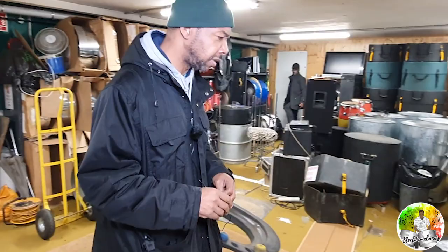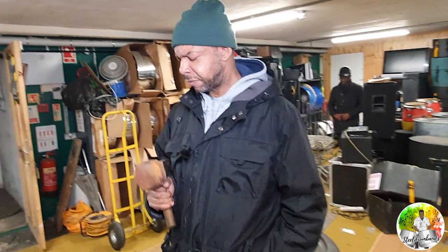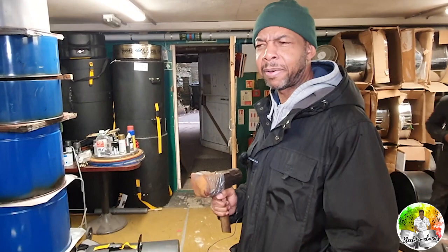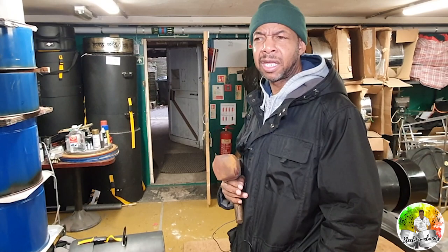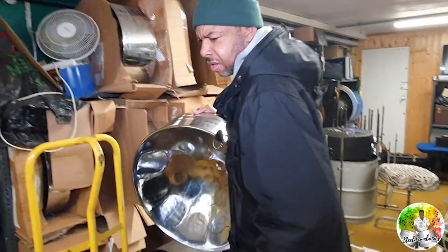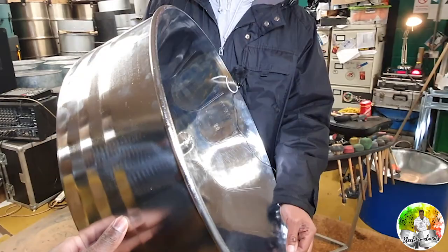This is like a sledgehammer — a seven pound hammer. So I don't need to go to the gym, I just deal with this seven pound hammer! And you sink down the drum. Now depending on what range of pan you're going to make depends on how far you need to sink it. For a tenor, they're generally about eight, nine, ten inches deep — quite a lot of stretching from cold. The basses are normally about four to four and a half inches. So that's a tenor there — you can see it's sunk quite low. It's a whole big panel-beating experience to get it down to that depth.